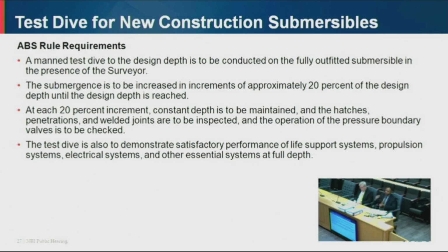Okay, you start diving and you increase your depth at 20% increments. So you first dive to 20% of your design depth, you stop, and then you will start internally inspecting all your welds, all your hatches, you will inspect your windows, and you will check your pressure boundary valves, make sure there are no leakages, okay? If everything is good, then you continue the test dive for another 20%, okay? In this manner, you keep going down till you reach your test depth, okay?